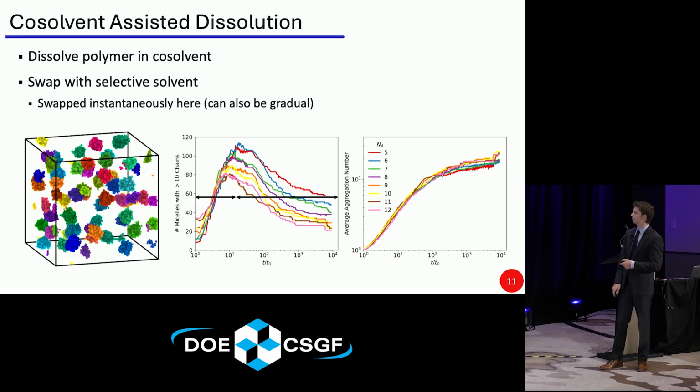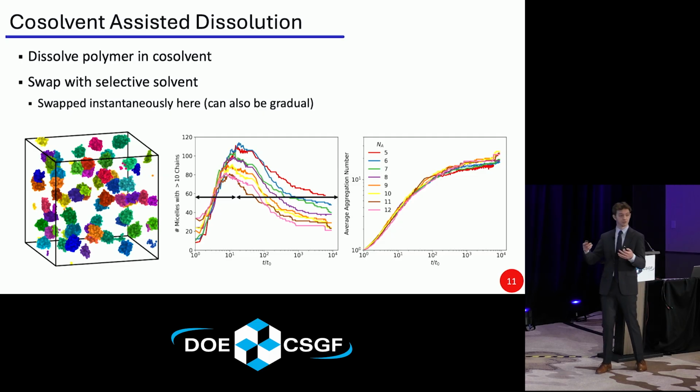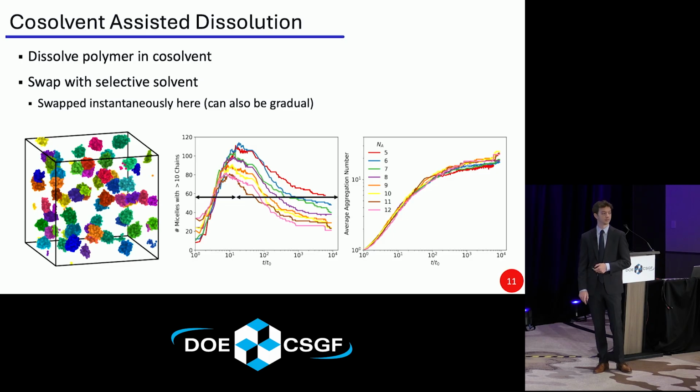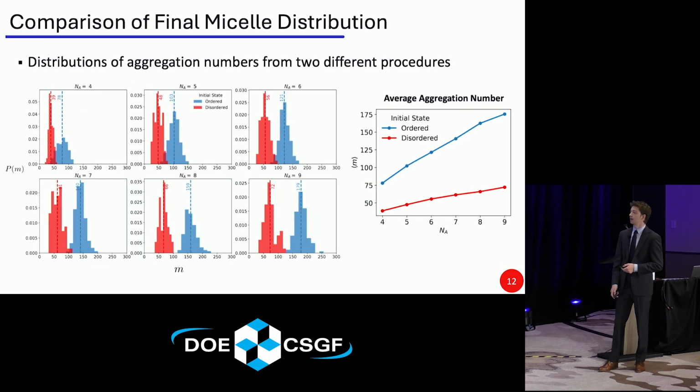And the main thing to note with this is that after that initial aggregation, which is at about t over t naught equals 100, the process slows down dramatically because of the strong barriers that I mentioned to the fusion and the exchange process. So this coarsening behavior is much, much slower than the traditional coarsening you expect in phase separation processes from, like, Cahn-Hilliard or something like that. Okay, I will wrap up in hopefully 1 minute and then have time for questions.